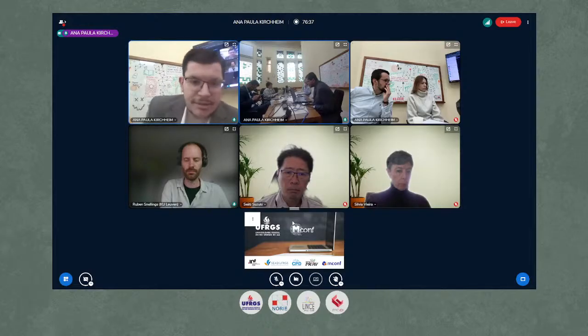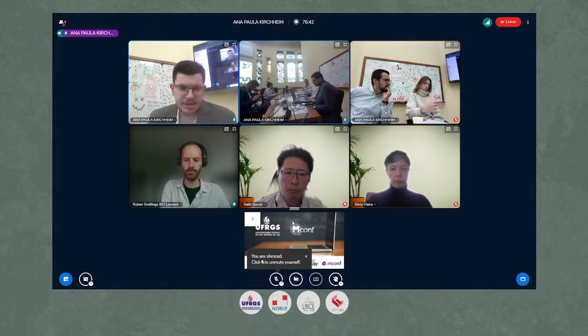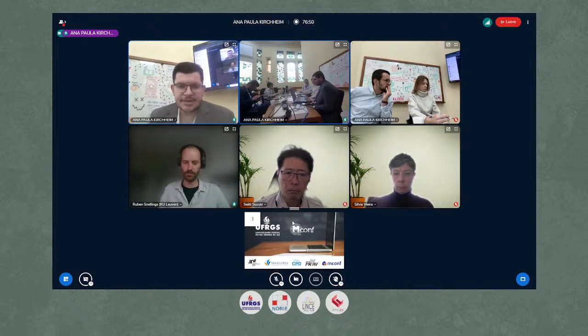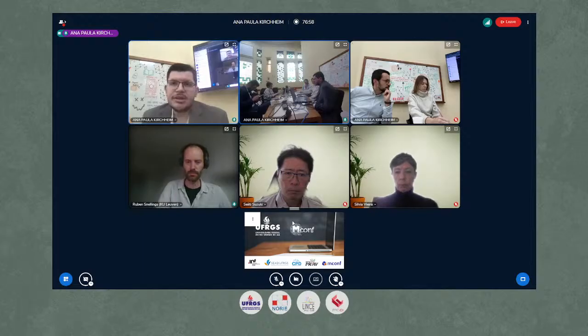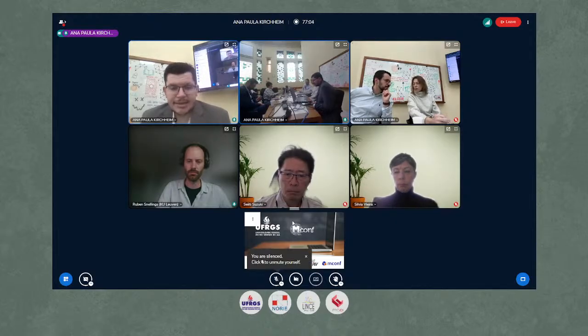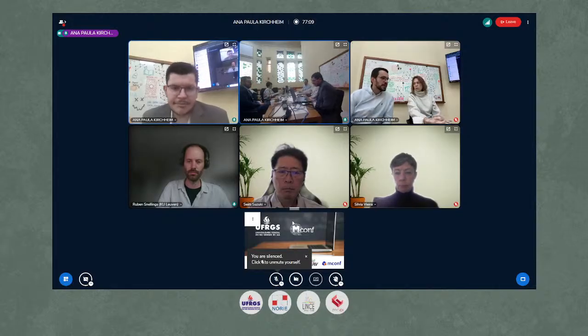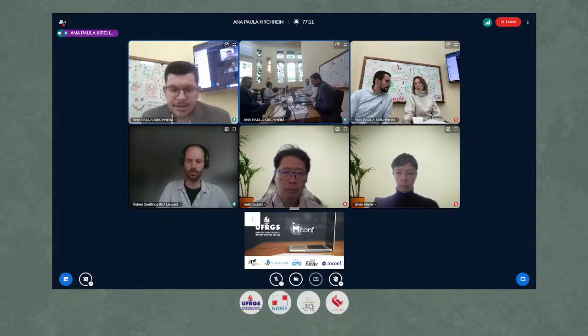So perhaps it's a very good idea to go deeper on this, on XRD analysis and other analysis, to try to calculate or identify the amount of defects in alite, and whether there is a correlation with the size of the crystals or the reactivity, but we didn't do this. We determined the crystalline size of alite in XRD, which is different from the crystal size in optical microscopy, but maybe it indicated the effect. But I didn't run any analysis on that.